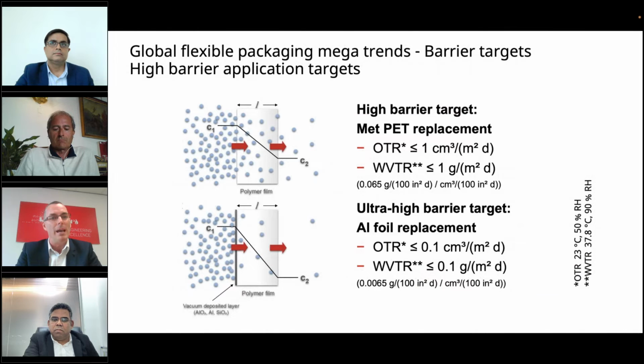In terms of the barrier requirement, for higher barrier applications, the market requirement generally falls into 2 main barrier levels. The first one is what we call metallized polyester replacement, where the market requirement is to achieve an oxygen and a water permeation rate of less than 1 cubic centimeter per meter squared per day and 1 gram per meter squared per day, respectively. And then we've got a second target, which is what we call ultra high barrier, which is to replace aluminium foil for flexible packaging, where the requirement is to achieve an oxygen and water permeation rate of less than 0.1 and 0.1 respectively. Next slide, Ben.